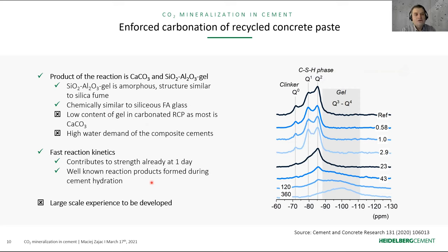As I told you, the alumina silica gel is a pozzolanic material. And we know, of course, more about the properties of this gel. The first one, we know it is an amorphous material. And from NMR study, an example you see here on the right-hand side, we know that the structure of the gel is similar to the amorphous phase, for example, in the fly ashes. And this has a lot of advantages.